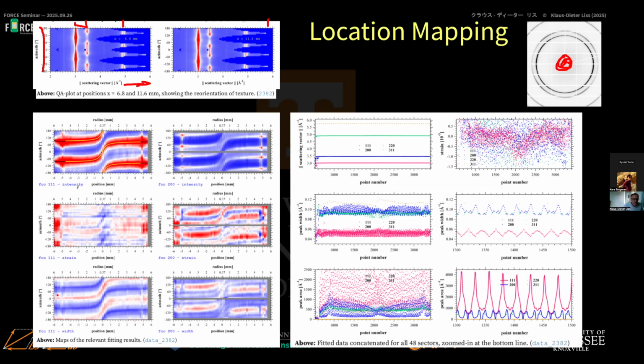So now, as a function of position, we can do that integrated over the whole ring, or we can sectorize it. When we sectorize it, we get those figures here on the right. So sectorizing, we get a lot of points, because for each position, there may be around order 100 positions, order of magnitude. For each position, we get 48 sectors, and they're all plotted here. So if I zoom into a small space here, point numbers 1300 to 1500, then I see the individual cycles. So from here to here, roughly speaking, is one position. From here to there is the next position. From here to there, the next position, and so on. So I can sort them out into a position,